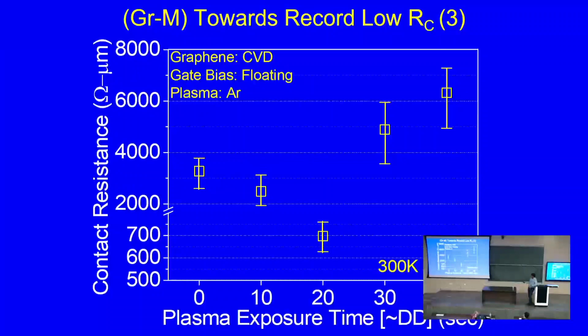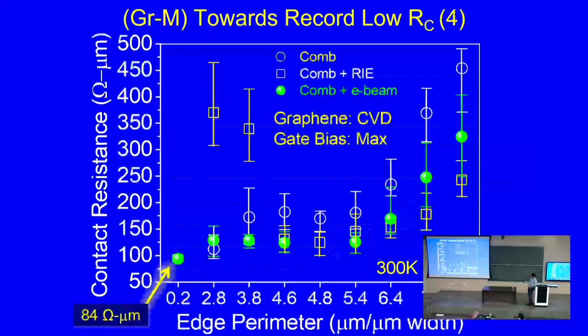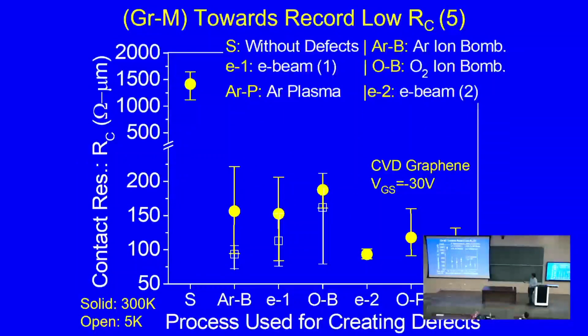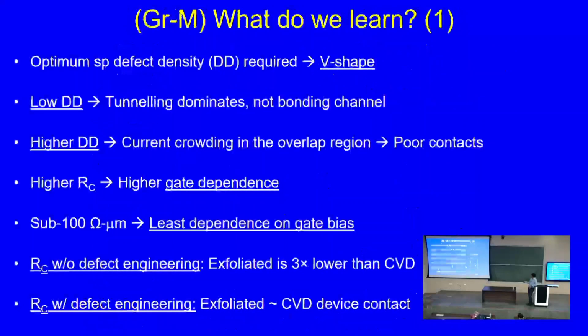Now this was with argon plasma where the defect density was less, still you have an improvement in the contact resistance. This was the case when we had either burned with E-beam, with comb, or had this comb and RIE or just comb, and we found this optimum, with all these dimensional variations. So we got this optimum of 84 ohm micrometer. And if you compare now different approaches for CVD graphene, measured at room temperature, you see these numbers in the range of 100 ohm micrometer.